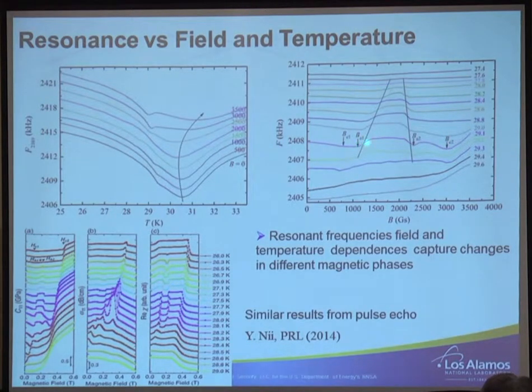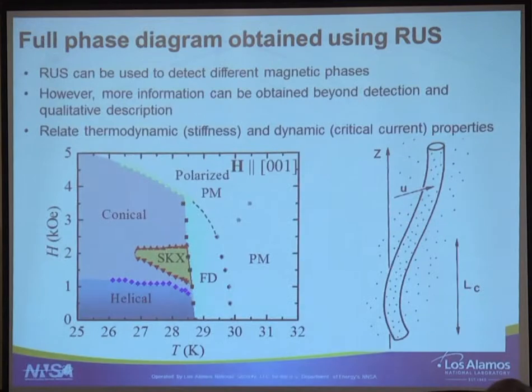You can see how, and this is again a frequency that depends on C11, so we see something that stiffens, and then this gets smaller as we go to lower temperatures. And both the place and the amount of change of the frequencies are consistent with the previous results by Nii et al. from a couple of years ago. Now, we can make a very good phase diagram of this, but this is not what we want to do.